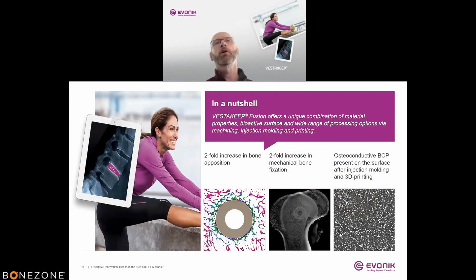So in a nutshell, we saw a 2x increase in bone apposition at the 100 and 300 micron distance off of the implant, which would be the more relevant distance, and a twofold increase in implant fixation for fusion versus unfilled or virgin PEEK. And when we assess under SEM or under high magnification, the osteoconductive biphasic calcium phosphate is present on the surfaces.